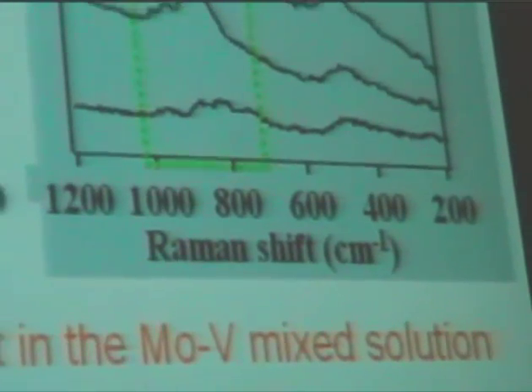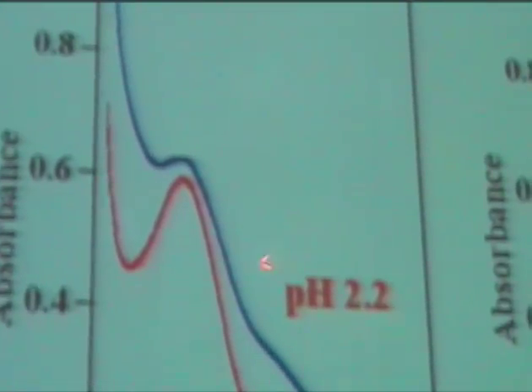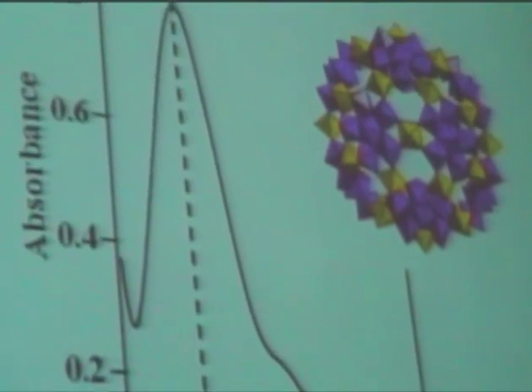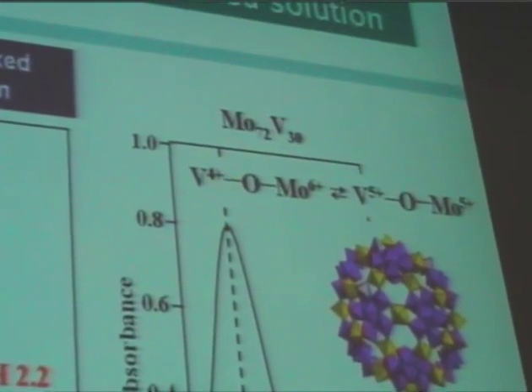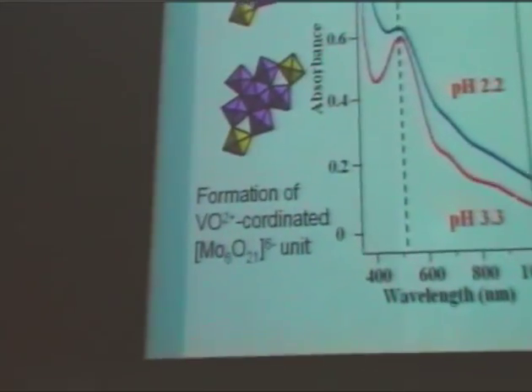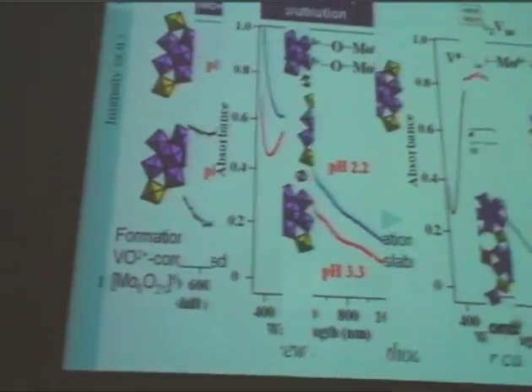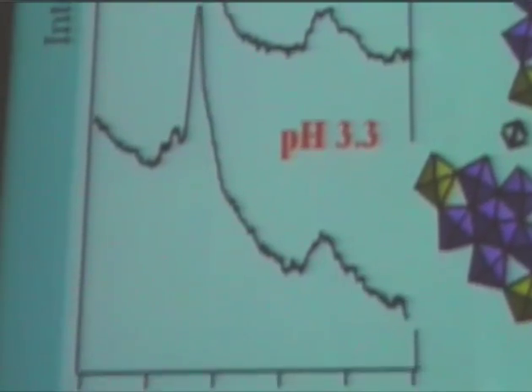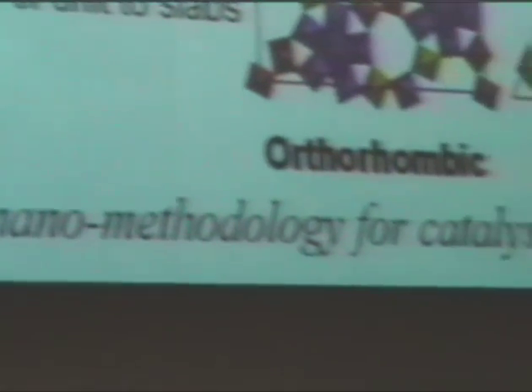So it is reasonable to say that we refer to these cluster balls — these forms — to be present during the hydrothermal synthesis. We also measured the UV-visible spectrum of the precursor solution and observed these bands, and this material has given features corresponding to the charge transfer between molybdenum species. So it is also consistent. This kind of evidence allows me to state why the structure forms — it is based on the pentagonal unit form. And when we got this solid, it gave exactly the same Raman bands in these regions. So obviously this material also has the pentagonal unit in the solid.